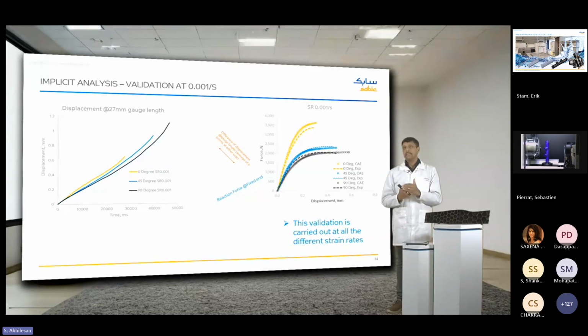So we take either the cross-head movement extracted from the machine when you're doing this test, and we input it in the solver, or we use a virtual extensometer to measure the end of radii displacements and input it in the solver. And once we do this, we measure a couple of outputs. We measure the reaction force, and we also characterize the strain occurring at node sets at the end of the parallel region, which is the gauge region. And these are compared against, again, experimentally extracted results.